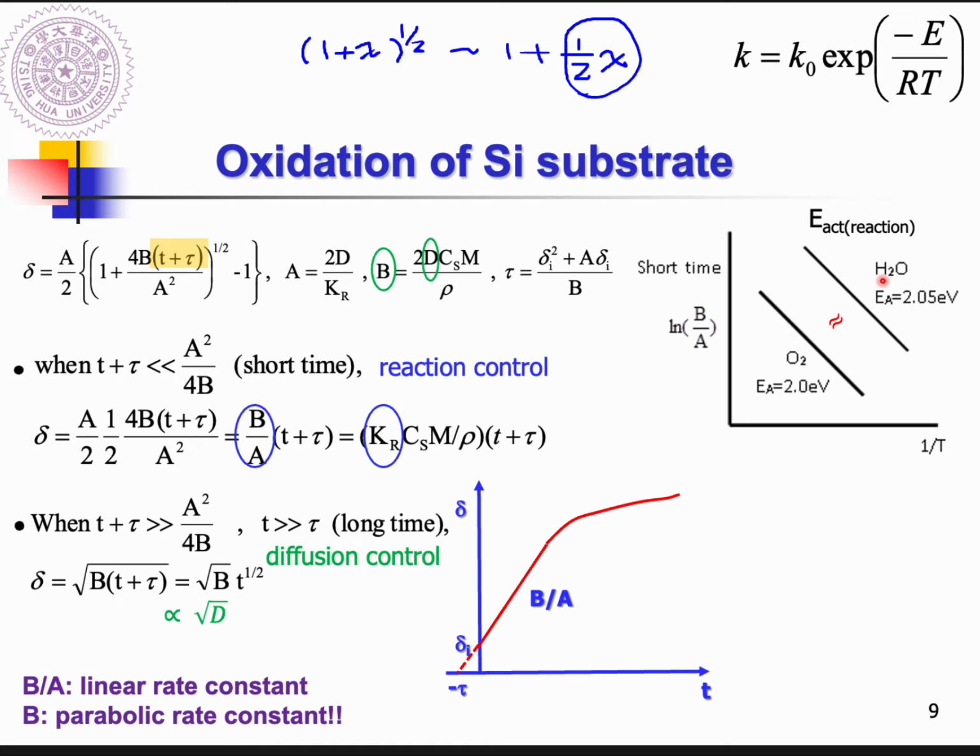In order to get silicon dioxide, for the reaction part, you need to break the silicon bond and replace it to form a silicon oxygen bond, right? So no matter whether you use the dry method or wet method, the reaction part has a similar energy barrier. Because it's a reaction, you need to break down the silicon bond. So the energy barriers should be similar, it's reasonable.